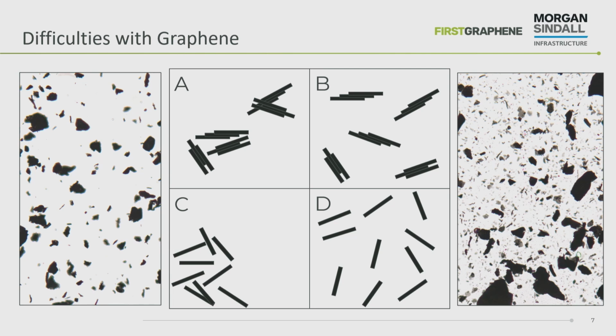platelets. That strength is imparted onto the cement paste, and the tensile strength of the graphene platelets brings a benefit to the hydrated cement. And doing this is very difficult, and it's difficult to supply a product which is stable. It's a formulation issue, really, that you've got to supply something stable and in those single platelet forms, which is